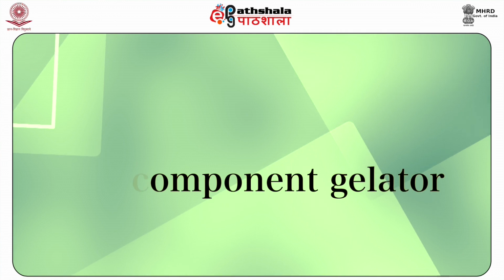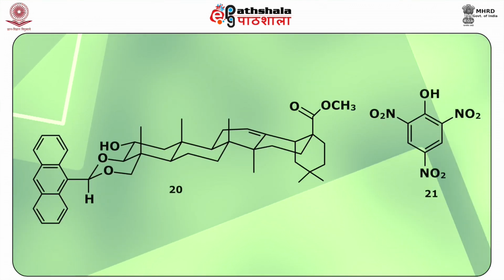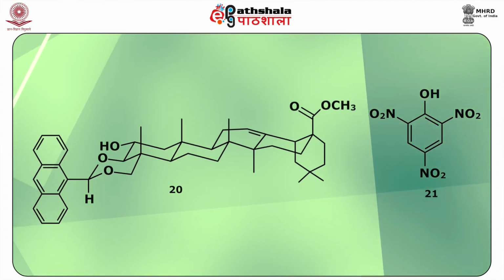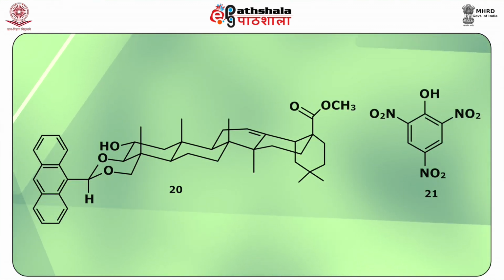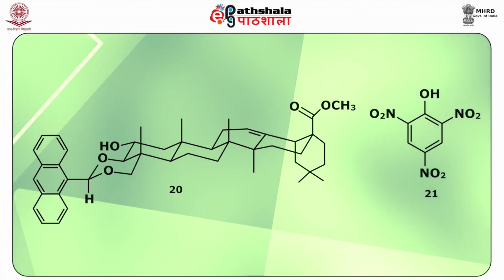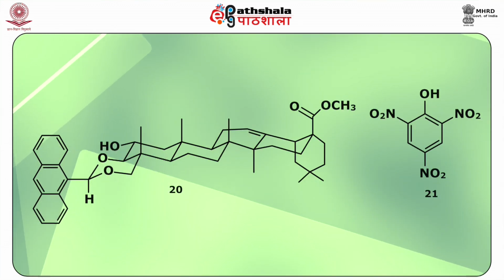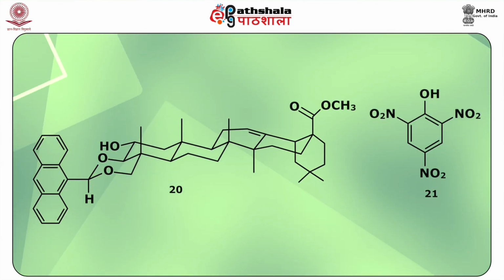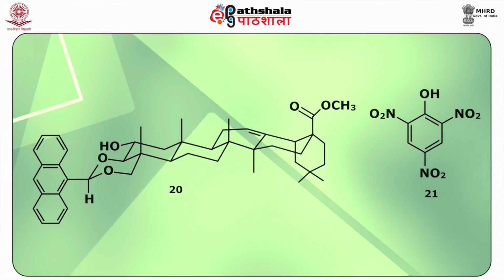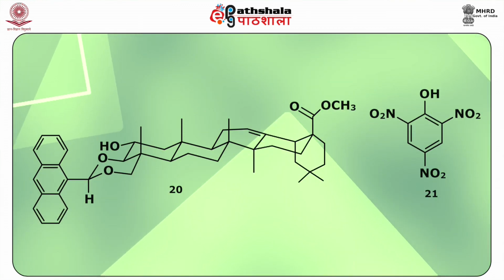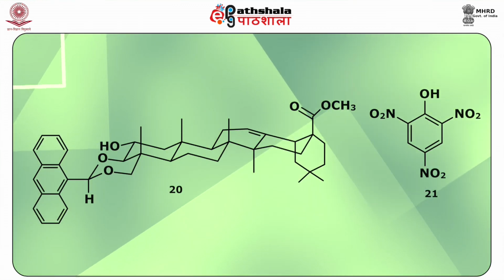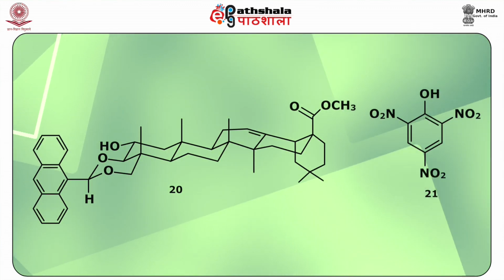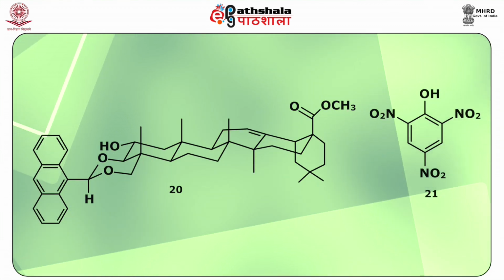Terpenoid-based two-component gelator. The derivative of the natural product arundoic acid forms a thermo-reversible gel with organic solvents in the presence of electron-deficient guests like picric acid. A change in color from yellow to deep red was observed during gelation. The charge transfer interaction between the aromatic part of the terpene derivative and picric acid has been observed and checked with temperature-dependent UV-visible spectroscopy.